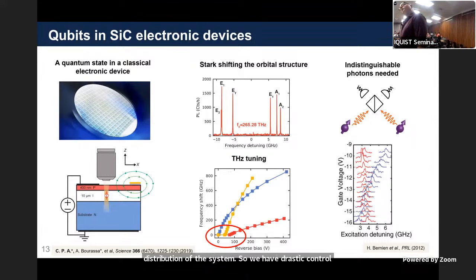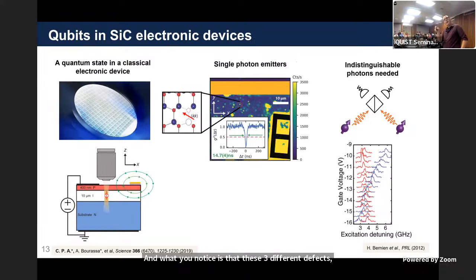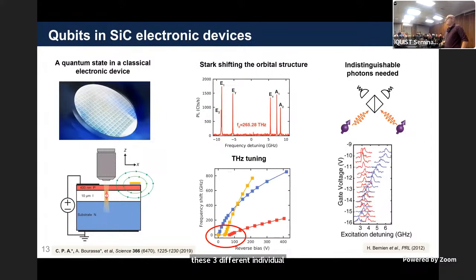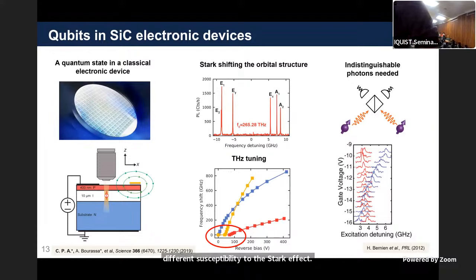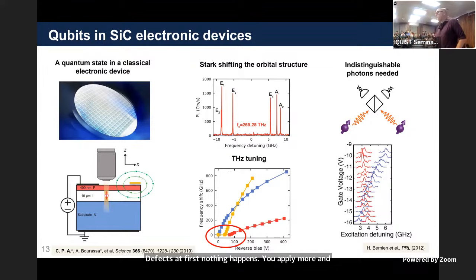These are example tuning curves of reverse bias versus the frequency of the emission. And what you notice is that these three different defects, these three different individual dots in this crystal, have very different tuning curves. And this is actually extremely important for understanding the physics of the system. One, they have different slopes, okay? Maybe there are different susceptibilities to the Stark effect. That makes sense. But the other thing is that for some defects, at first, nothing happens. You apply more and more voltage, and there's no shift. And then all of a sudden, they start shifting.